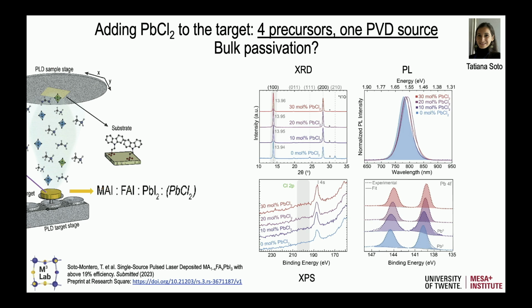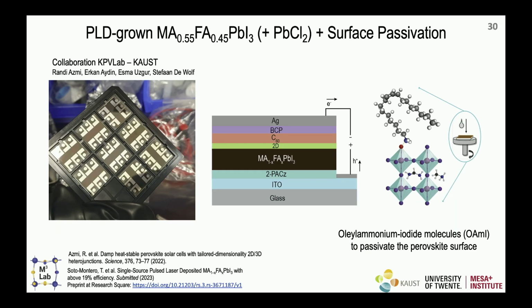But you see in the PL, I mean, there was some shift, but we are still also discussing that because it's not correlated to the amount of lead chloride. It seems to be more stress in the film. But in any case, we added lead chloride. Here we cannot say anything. We will see the results in the solar cell efficiency. Now, after the bulk passivation, we needed to do surface passivation.